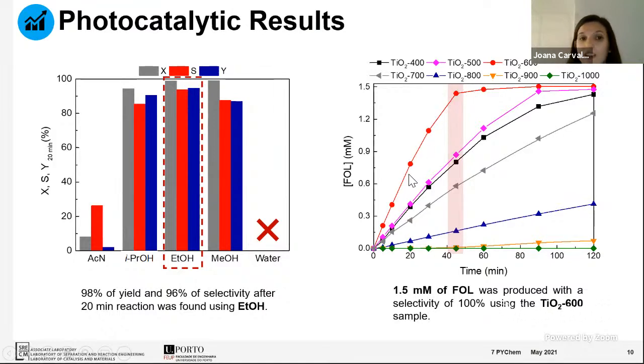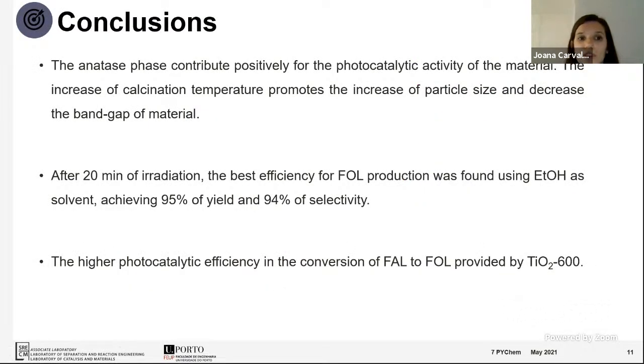In this way, with this work, I can conclude that the anatase phase contributes positively to the photocatalytic activity of the material. The increase of calcination temperature promotes the increase of particle size and decrease of band gap of the material. After 20 minutes of reaction, the best efficiency for furfuryl alcohol was found using ethanol as solvent, reaching 95% yield in the production of furfuryl alcohol, and high photocatalytic activity. It was obtained using the titanium dioxide calcined at 600 degrees.